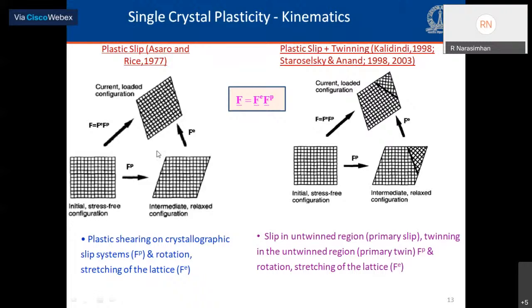If you take a look at the left side schematic, in the case of the Asaro-Rice formulation, Fp takes into account plastic shearing on crystallographic slip systems, whereas Fe accounts for the rotation and the stretching of the lattice. In the Kalidindi-Staroselsky-Anand formulation on the right side, Fp accounts for slip in the untwinned region and twinning in the untwinned region, which is called primary slip and primary twinning, whereas the stretching and the rotation of the lattice are vested in Fe.